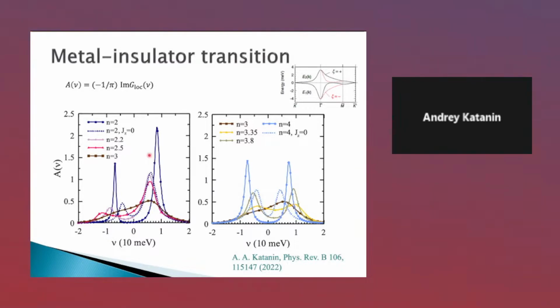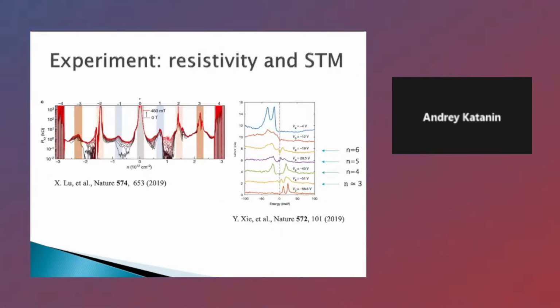For the even fillings, they form a Mott insulating state with a pronounced gap at the Fermi level, here for n equal to 2 filling of the moiré Brillouin zone, and here n equal to 4. And for the other fillings, they correspond to metallic states of the electrons. This agrees with the experimental observation that the resistivity increases at the even integer fillings, like we obtain for the spectral functions, and the form of the spectral functions even qualitatively agrees with some STM spectra which were taken on small angle twisted bilayer graphene.